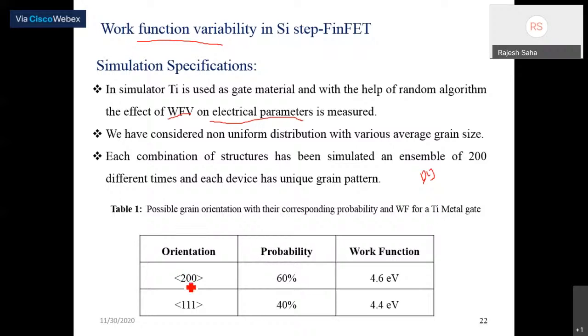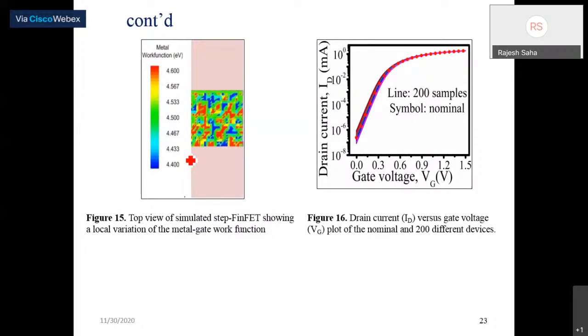These are your work function values, and the probability of getting each value we have taken from the experimental paper. In the orientation 200, the work function value is 4.6 for the titanium metal gate. Similarly, in the orientation of 111, the work function value is 4.4 electron volt with probability 40%. We have considered these values in your TCAD simulator. As you can see, this is the top view of the randomization of the work function within the gate area, ranging from 4.4 to 4.6. And in figure 2,